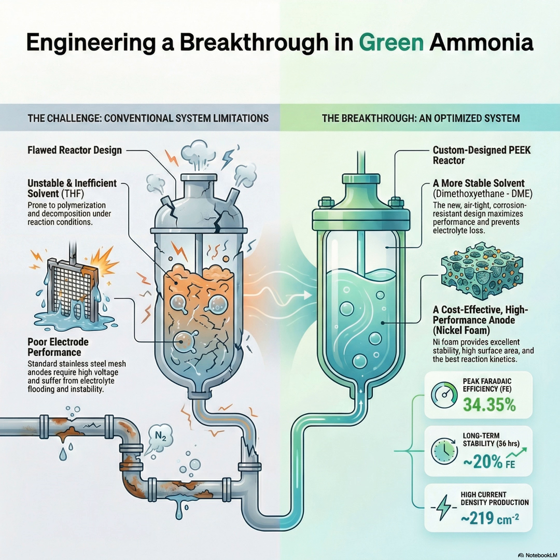What did this combination actually achieve? Well, the performance leap was huge. It totally validated their whole engineering approach. Remember that initial commercial setup? That only got them about 9.4% Faraday efficiency. Right. Once they moved to their optimized peak setup with the nickel foam, that peak FE jumped to an impressive 34.35%. Wow. That's nearly a four-fold increase in efficiency. That's the difference between a science project and something that could actually be competitive.